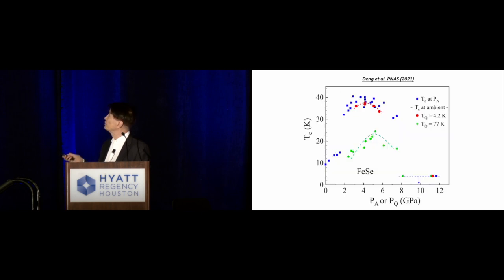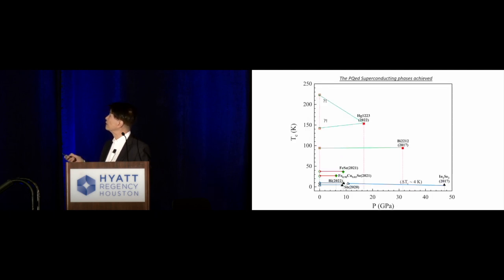So now we already have some preliminary success. For example, in one of the compounds we did, originally it was not even superconducting, and on this scale you really look at zero, it's not even superconducting. But when you apply pressure, it can become superconducting. And when you remove the pressure, you can maintain the superconducting state without pressure, as indicated here. Depending on the quenching temperature, one is 4.2 K and the other is 77 K. You remove the pressure, it's still superconducting. So that's why we are very excited about that.